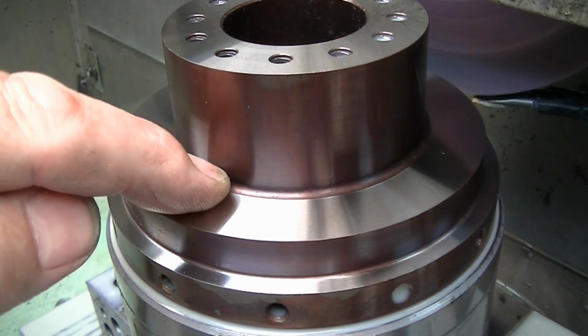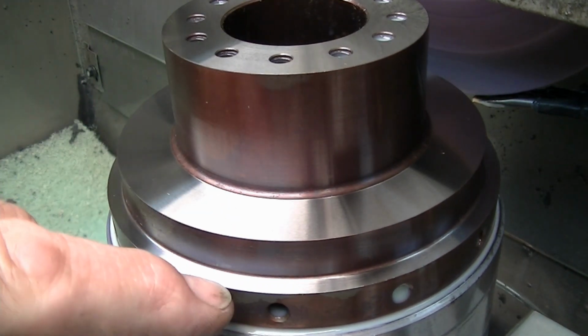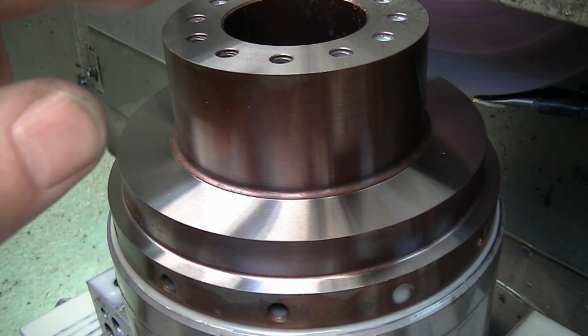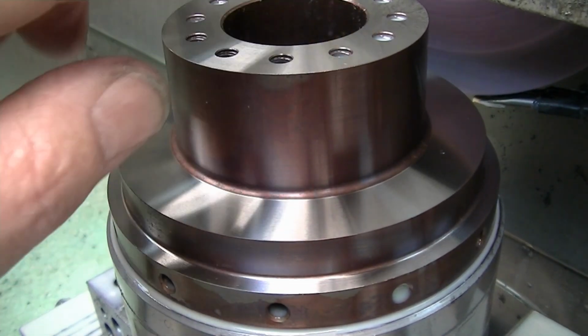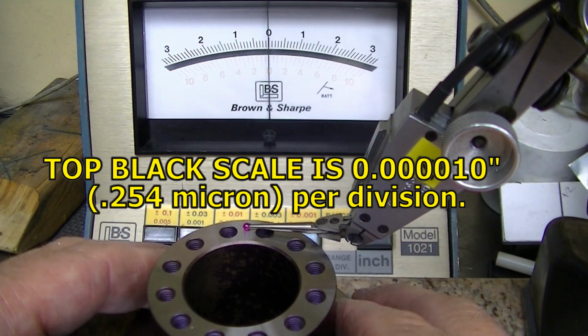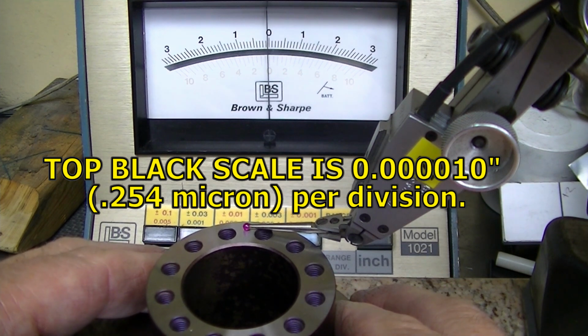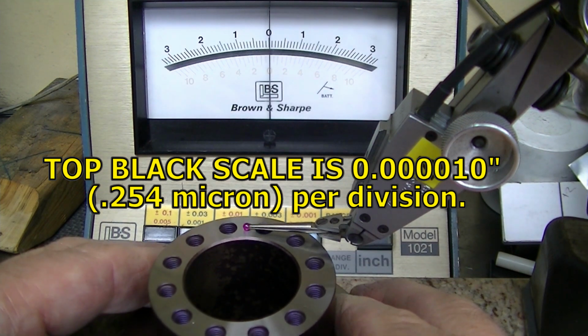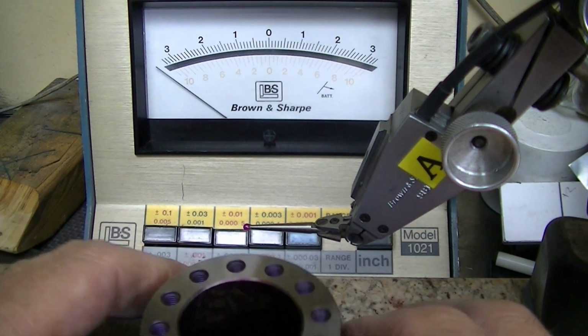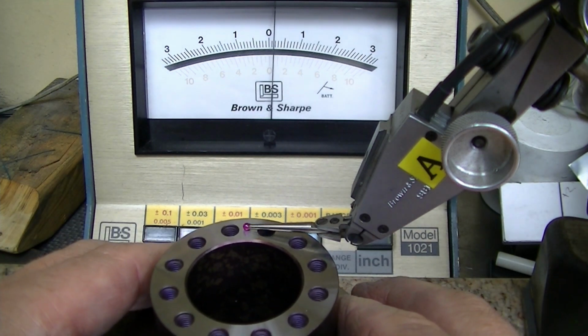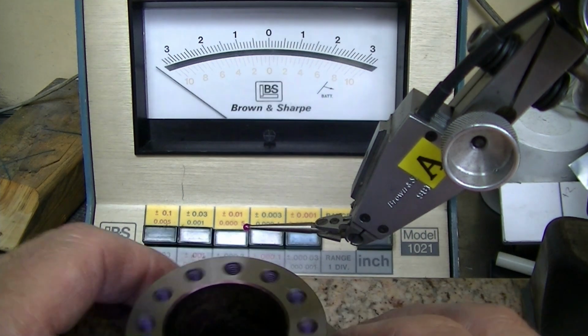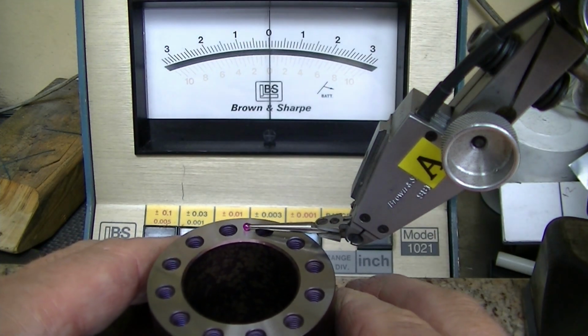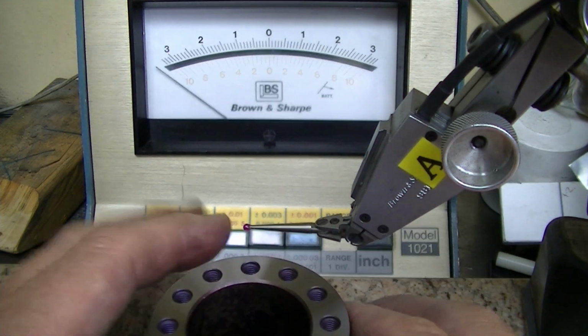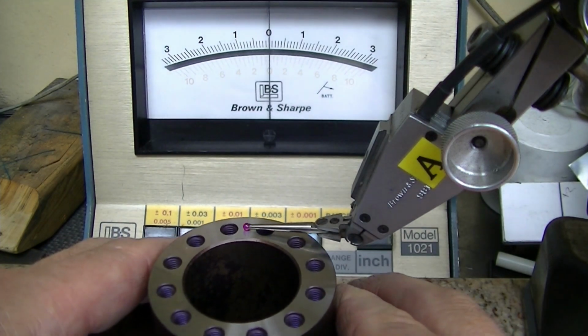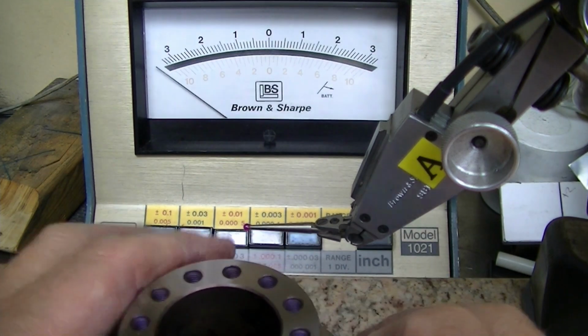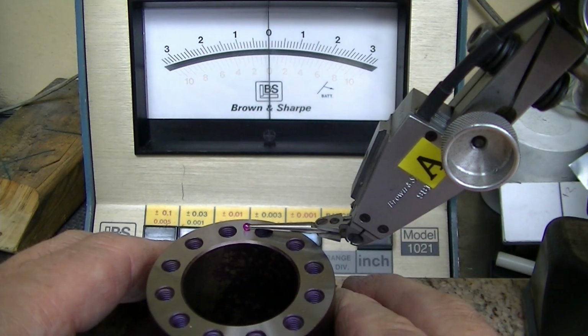There's the bearing race surface that was ground, and the seal surface that was ground, and the upper bolting surface that was ground. Here we're measuring the back clamp face that we did first, actually. There's 0 there. 10 millionths. 5/10 millionths. 5/10 millionths. Back to our 0.